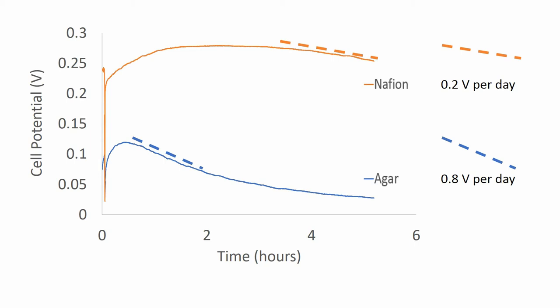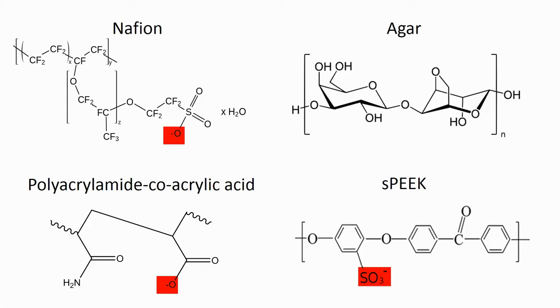Agar cell 1 seems to have a much lower voltage. That's probably because it's actually discharging essentially immediately as it penetrates through the agar upon setting up the steady state, and then it loses 0.8 volts. So over the course of two or three hours it will lose all of its potential. So we need something a little better.